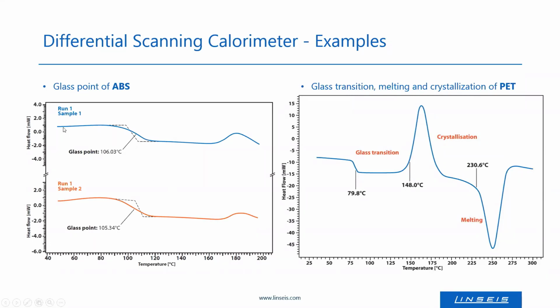And here you see clearly the glass point in the two curves, and you see that both samples show a really similar glass point. So by that, you, for example, know that the heated tray should be lower than 106 or 105 degrees Celsius to keep it slightly below the glass transition point.